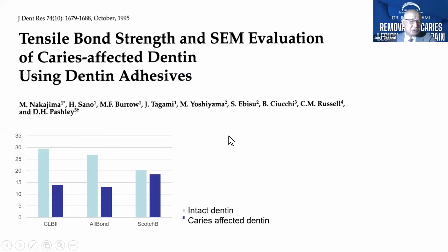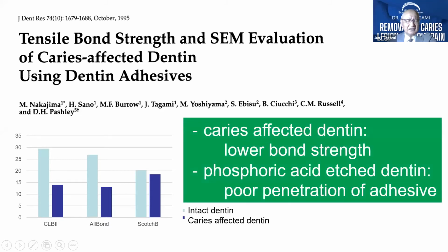This is a very old paper, but very important to have shown that the caries affected dentin could not be bonded very well because of a lower percentage of the mineral phase of the dentin. And also, if you apply phosphoric acid etching to this caries affected dentin, the bonding is very poor because of very poor penetration of adhesive into the phosphoric acid etched dentin surface.